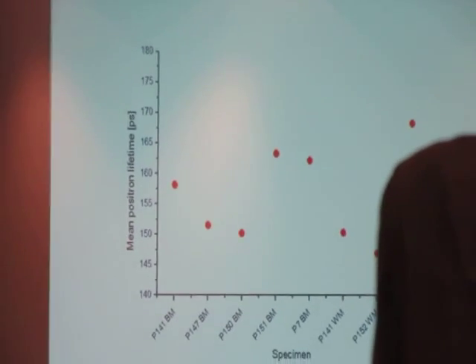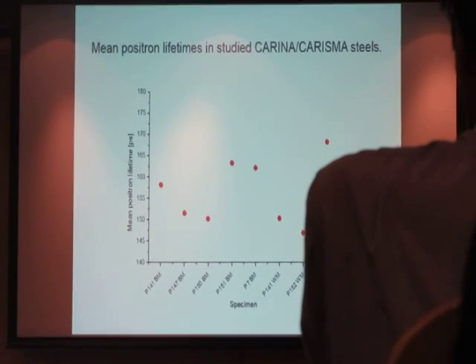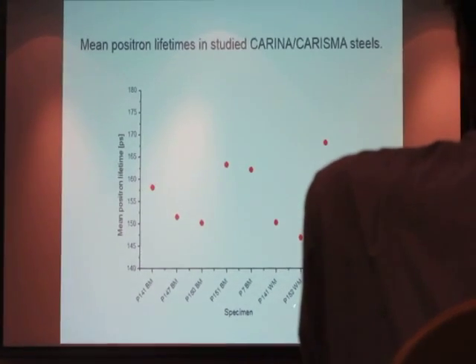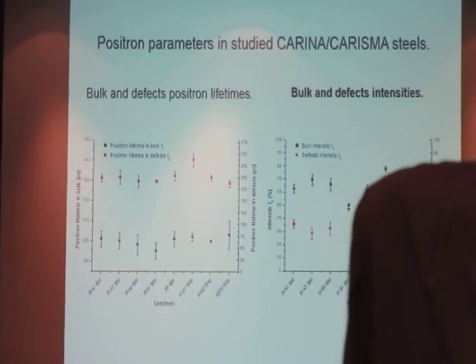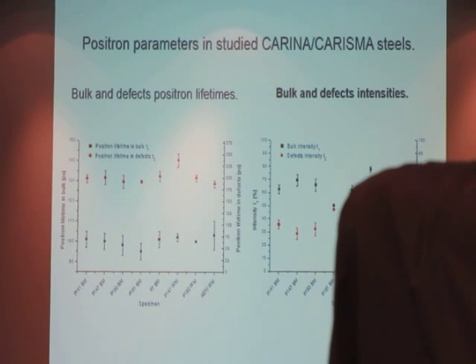The mean lifetime in all these not irradiated specimens is different. And this difference is caused mostly by the copper content. This one is 0.22 copper. Copper is now kept under 0.08% of the weight. It's the limit for the new steels. Good. If we make a two-component analysis, let's say according to the standard trapping model, we have the first component about 100 picoseconds, and the defect component is almost stable at this level, let's say 130, 140. The intensity of the defect component is quite high, let's say 30 to 40%.